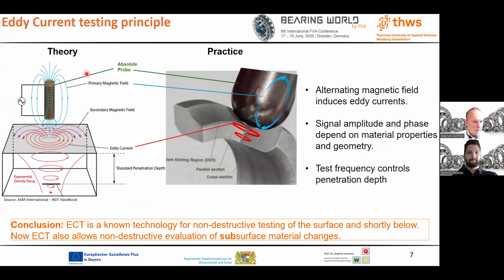And now, how does eddy current testing work? In theory and in practice. So here is the probe, and the probe is producing a magnetic field, the blue lines. So this is the probe in practice, and these are the blue lines of the magnetic field. And this is inducing eddy current into the material, those red circles here. This is the eddy current that is induced into the surface, into the material of the inner ring. So the conclusion on this slide: eddy current testing is a known technology for non-destructive testing of the surface and shortly below the surface. But now, eddy current testing also allows non-destructive evaluation of subsurface material changes.